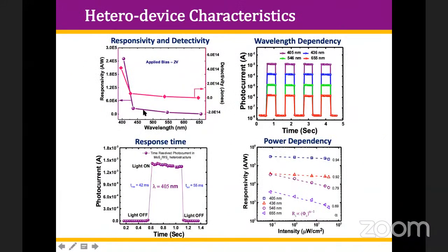You can see here, as a function of wavelength, 405 nanometer gives the best responsivity as well as the detectivity. Both are found to be very, very high at lower lambda when applied bias is 2. And these are the responses for the heterostructure, not the individual layer. You can see also the repeatability, and the response was found to be much, much higher. The dark current is the same in all the cases at all wavelengths, but the photocurrent is maximum at 405. Response time and recovery time, you can see 42 milliseconds and 56 milliseconds, have been obtained.